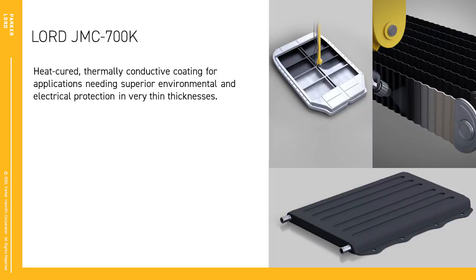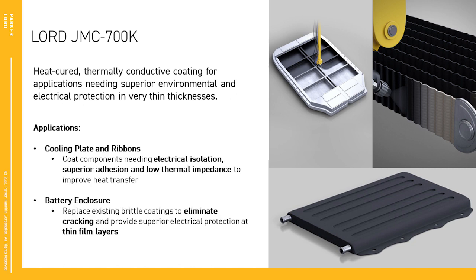So LORD JMC 700K is one of our thermally cured options. It's most commonly used on cooling plates or cooling ribbons. It's applied at around 90 microns, and that'll give you what most OEMs require for dielectric resistance. It's spray applied using standard HVLP equipment and can easily be automated. It has good flexibility and good crack resistance and can withstand temperatures in excess of 180 C during the operation of its end use. And it's a really good alternative to powder coating, where powder coating struggles around edge coverage because of its electrostatic deposition or because of some cracking or something like that.